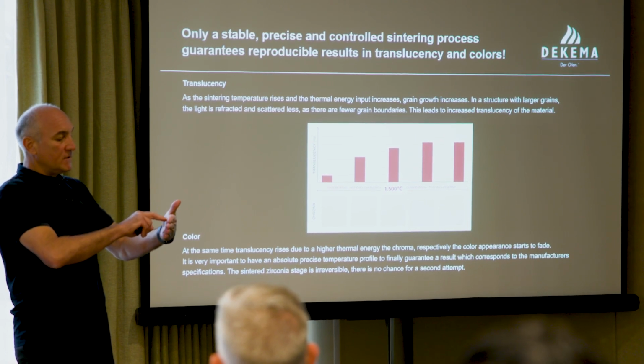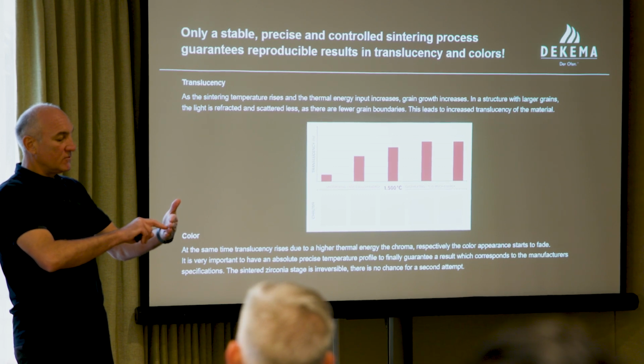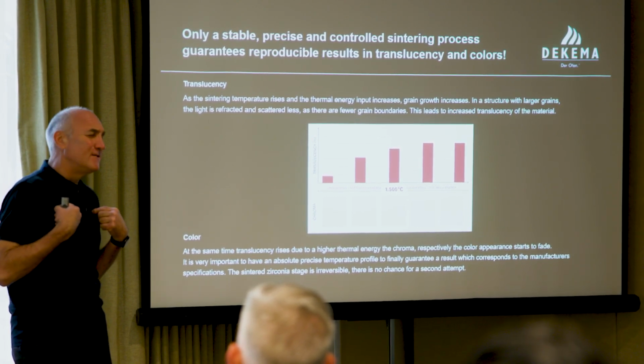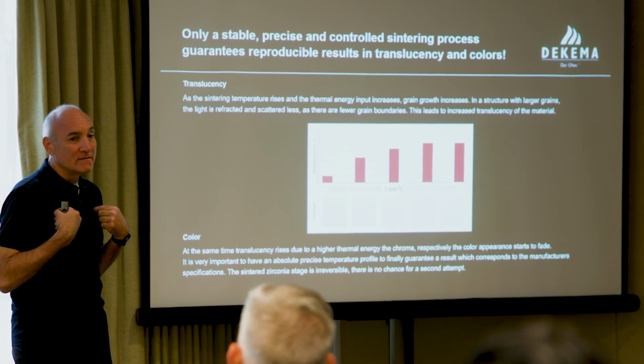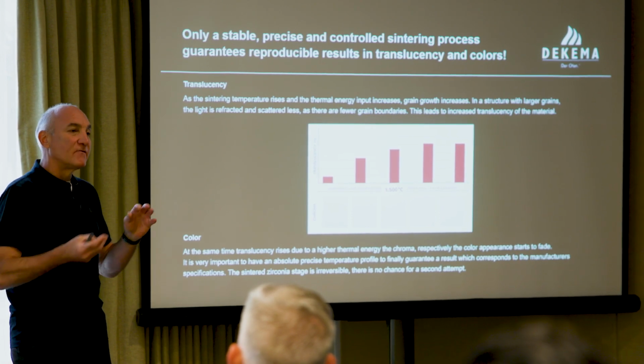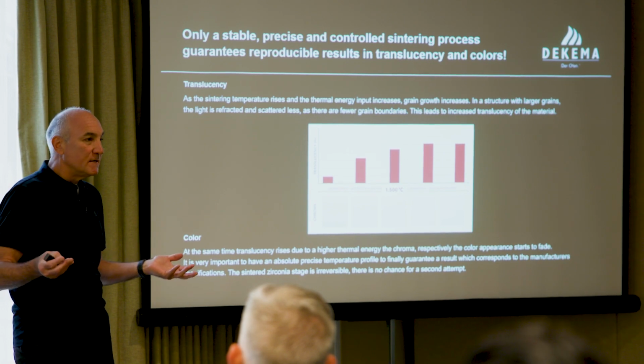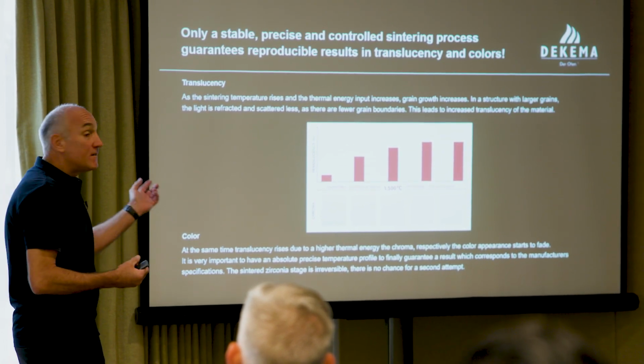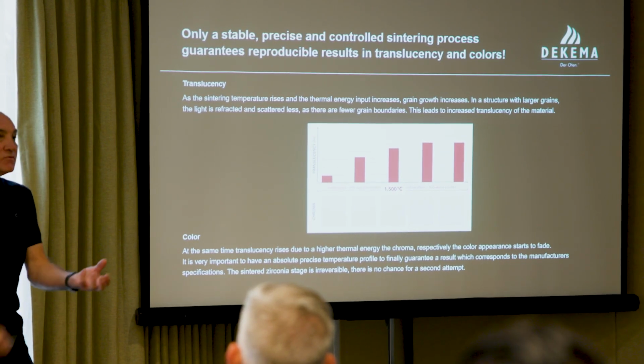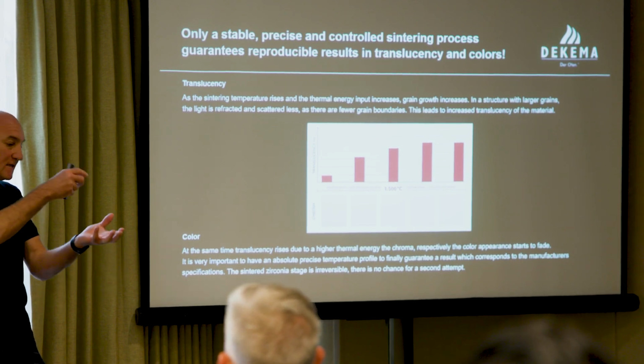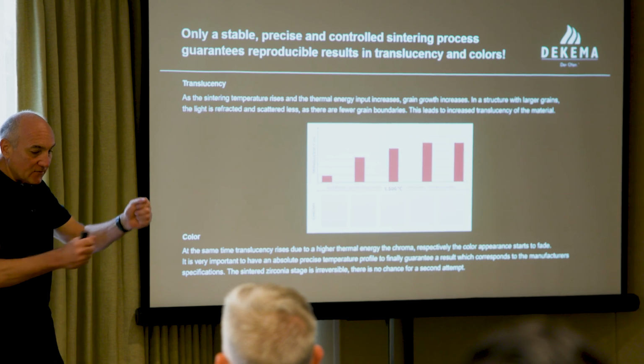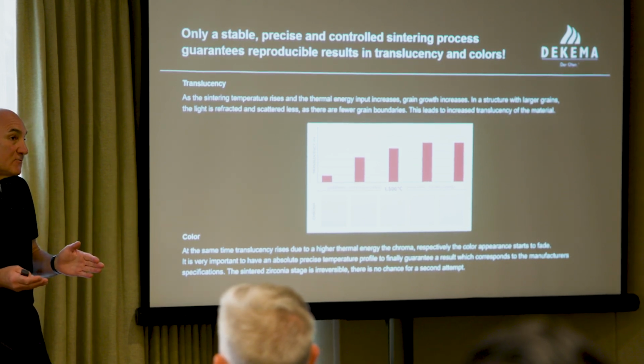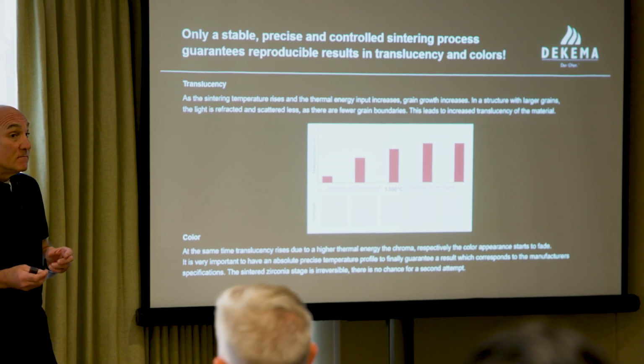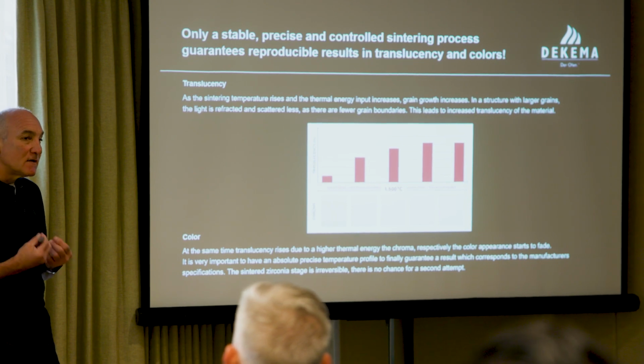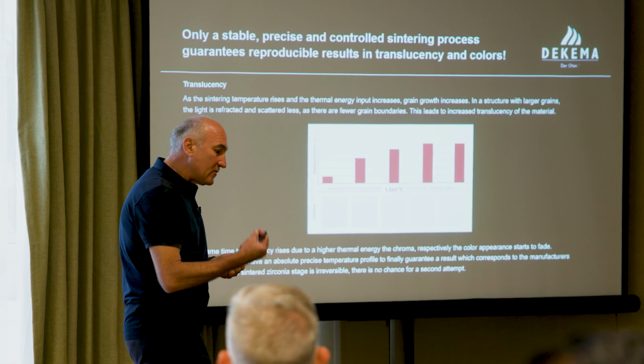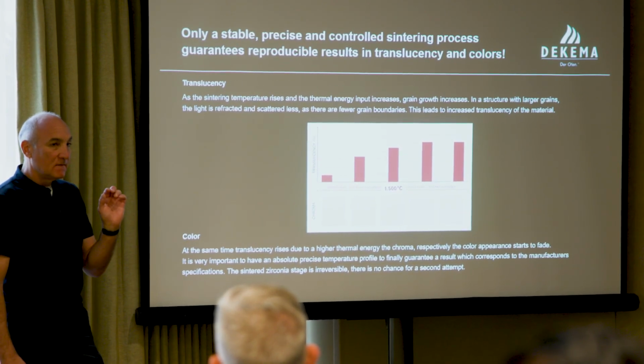if your PTC ring shows a deviation of more than 10 degrees, you should recalibrate it. If I talk of calibration at more than 10 degrees, you would never have to calibrate a DEKEMA furnace till the thermocouple is broken. But through ISO and customers who want to calibrate, typically once a year, we need to have an easy tool, not too expensive. With the previous furnace, we had a calibration with an external thermocouple, which was $2,500, because you needed a special insulation table, you needed special evaluation electronics, and so on and so on and so on. This is what was sold more or less to every 3M service engineer. Good for us, but not for the customers, because they couldn't calibrate themselves. So now we found a solution how to calibrate DEKEMA furnaces with PTC rings the right way.